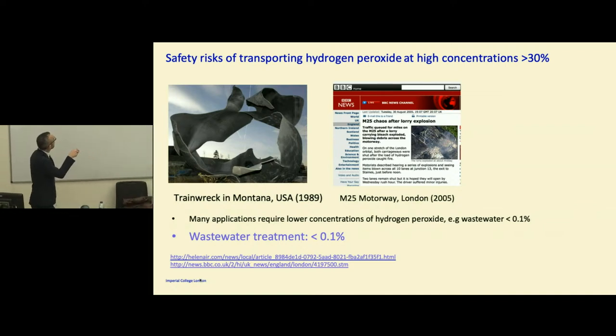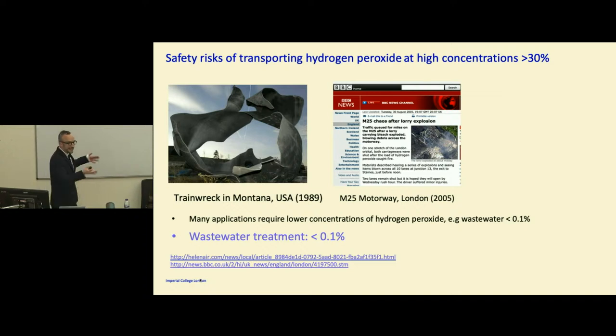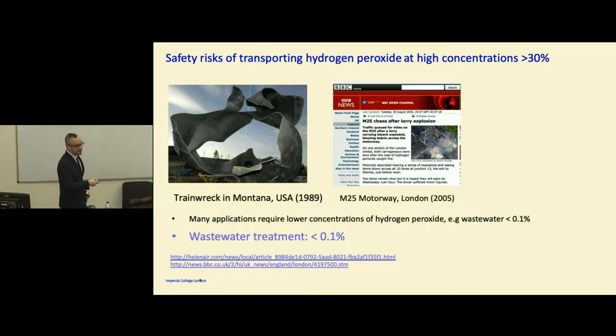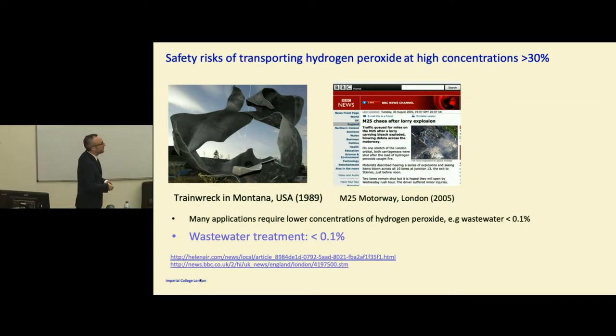There have been two very well-documented accidents, including one on the M25 motorway, where people had a big canister of hydrogen peroxide. It broke apart and exploded. Usually, if you're trying to clean water, you only need a really, really low amount of hydrogen peroxide, around 0.1%. So we started talking to people in industry and said it would be great if you could actually use electrochemistry for making hydrogen peroxide.